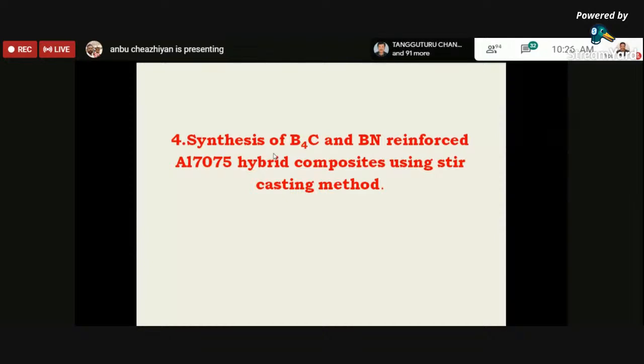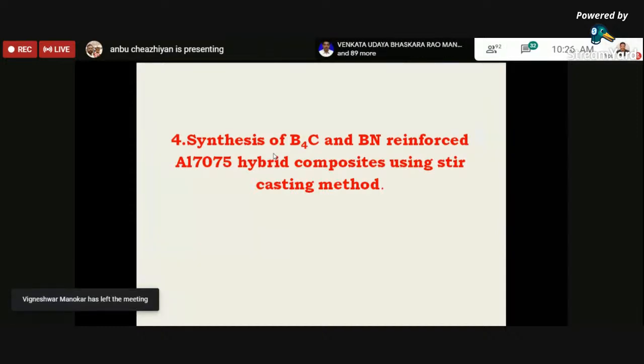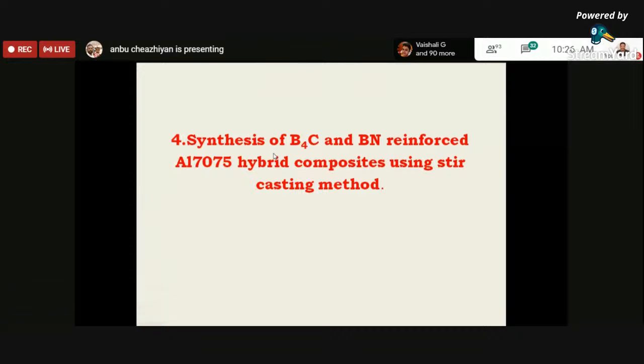This is because of boron nitride compared to the other reinforcements. Boron nitride exhibits a lamellar crystalline structure with significant lubricating properties. In addition to that, boron nitride has high thermal conductivity, low thermal expansion, superior shock resistance, and excellent castability. So considering that, we have chosen boron carbide and boron nitride. One is a hard reinforcement, another one is a solid lubricant.